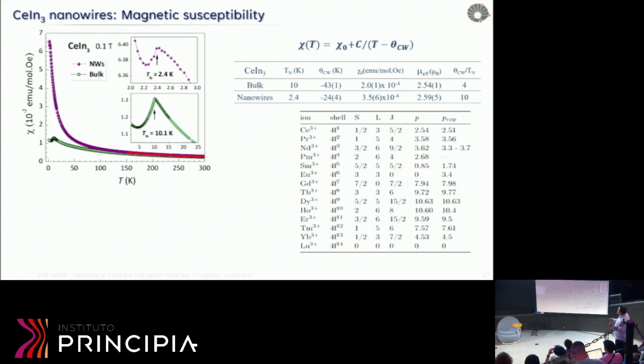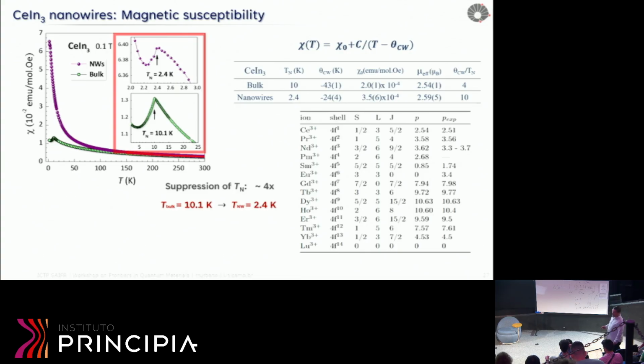Here's what we found for susceptibility. As we observed for cerium indium-3, here we also saw this huge suppression if you compare nanowires and bulk. So it went from like 10 Kelvin down to 2.4 Kelvin. But now if you look at the moment we analyzed, the Curie-Weiss model is not so far from the cerium 3+, so everything is working just fine.